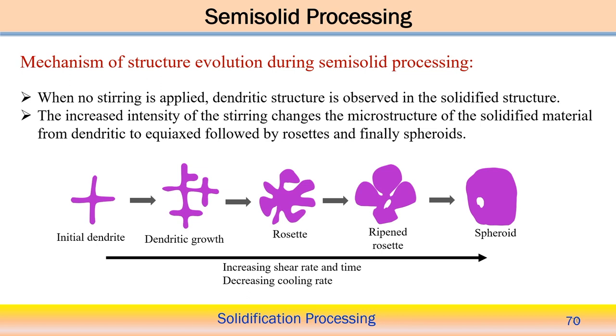Because we are not applying any external force, we can expect some kind of dendritic structure, allowed to form freely during solidification, without any external stirring action. Now, if we increase the intensity of the stirring, that changes the microstructure of the solidified material from dendritic structure to an equiaxed kind of structure, followed by different kinds of rosettes, and finally it reaches a spheroid kind of shape.